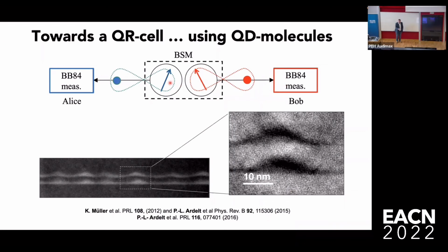And then what you need to do is a Bell state measurement on the quantum memories in order to establish entanglement swapping between Alice and Bob in the way that Christoph described earlier on. These quantum dots have the nice ability that if you grow a layer of quantum dots, and then on top of that you grow a second layer, the second layer of quantum dots nucleate directly above the first.